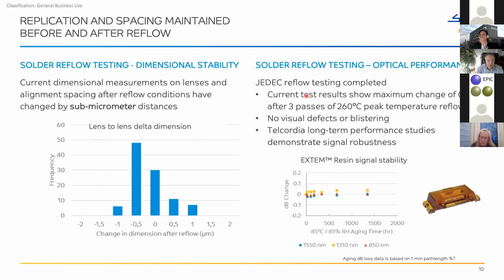So here at SABIC, we have our own reflow machine and our own confocal microscope. So we looked at doing reflow with this connector at 260 degrees Celsius for 3 times. And we see a negligible dimensional change. I mean, it's well below 1 micron. Well, remember the spec was 30, right? So this is pretty good.